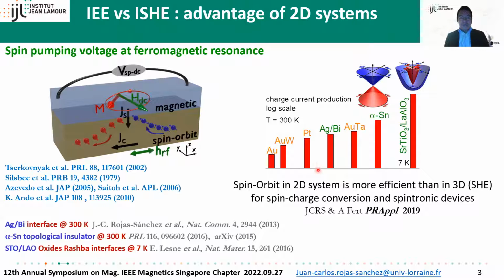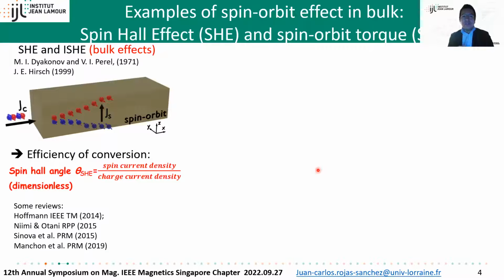Okay, but this is a reciprocal effect that we can use with this tool to quantify. But for application, we're interested in the direct effect. Due to the spin Hall effect, we know that when we inject a charge current, we have a spin accumulation at the interface, and if we attach another magnetic layer, for example with perpendicular magnetization, we can manipulate this magnetization.